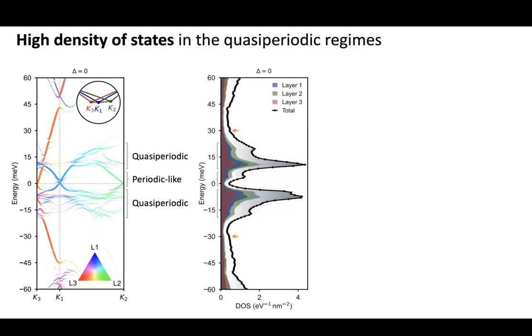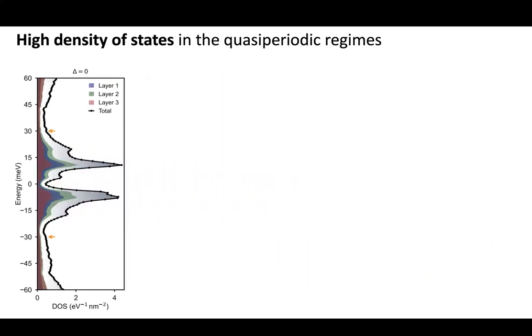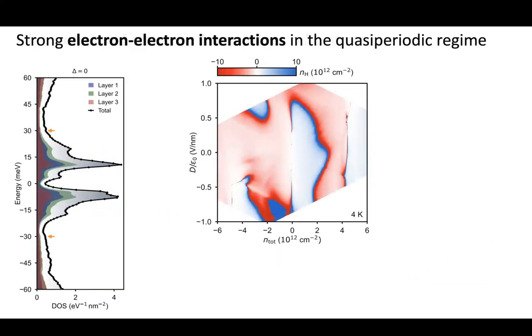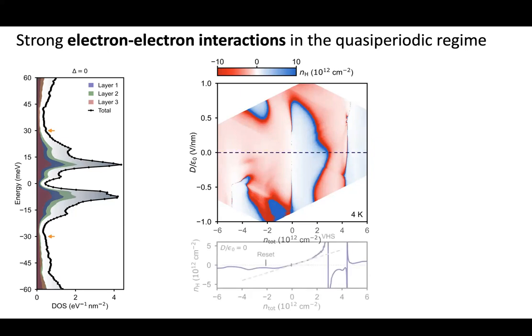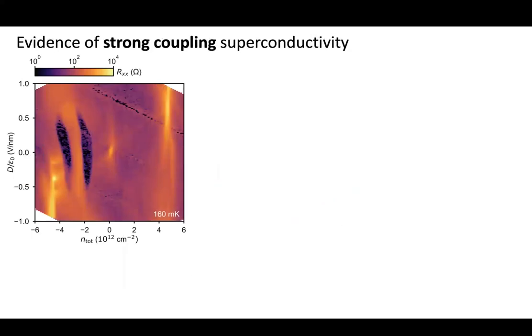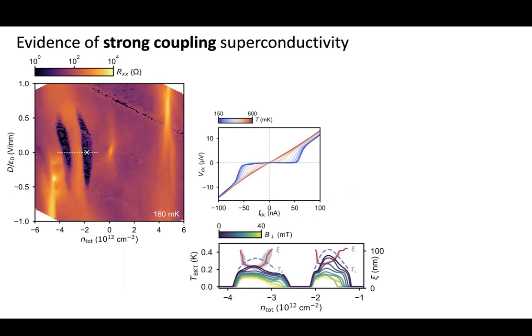You can calculate the density of states of this system. And you can also do a Hall density measurement, which, although I haven't discussed this, in magic angle bilayer and trilayer graphene, lots of experiments have shown that at these integers, you have a change in the Hall density. We call them resets. They have various names, and they are actually phase transitions, reconstructions of the Fermi surface. It turns out this also happens here. Rather than going along this straight line you would see for a single particle, it has this reset, which tells you that interactions are happening and doing something. And on both sides of that reset, of that phase transition, we have superconductivity. We have superconducting domes.